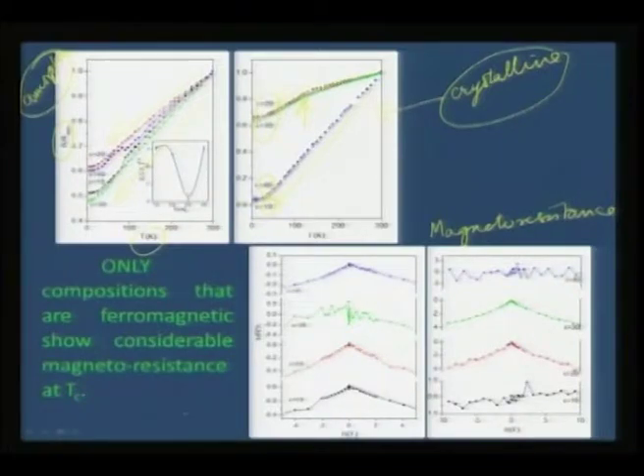this is for the amorphous pattern, or for the amorphous sample. You can see in the amorphous sample almost all the samples show this sort of MR behavior, meaning the resistance is maximum, but as you sweep the field the resistance drops down. So, even though the magnetoresistance ratio is feeble, not of a very high order, you can see in all cases it is turning that way, whereas in the crystalline phases, in the crystalline compounds, you can clearly see the